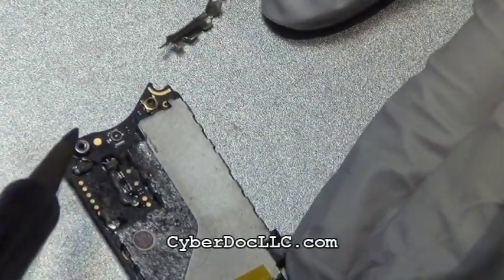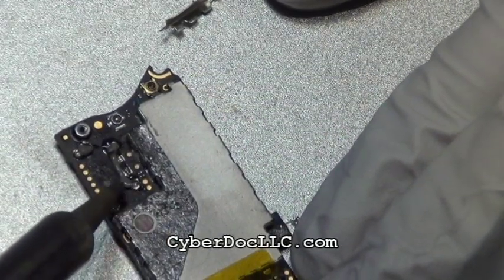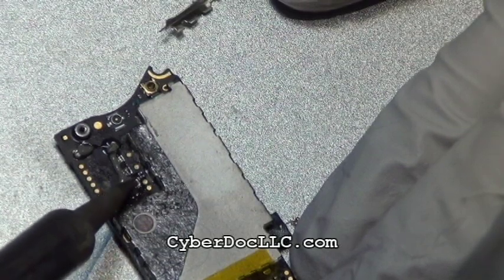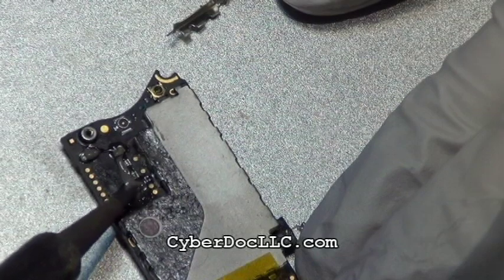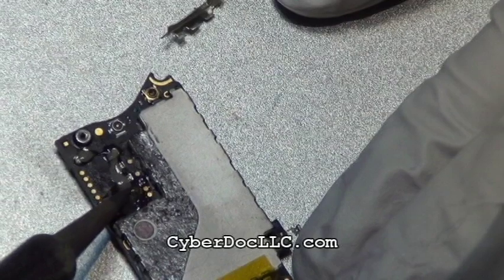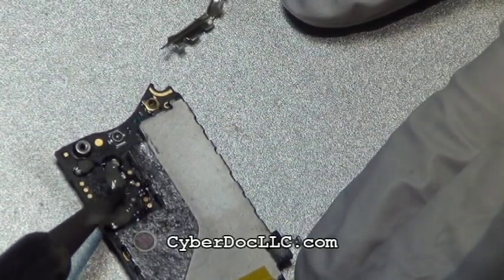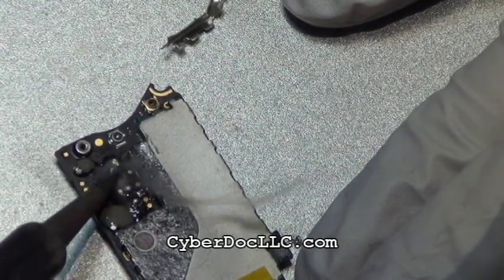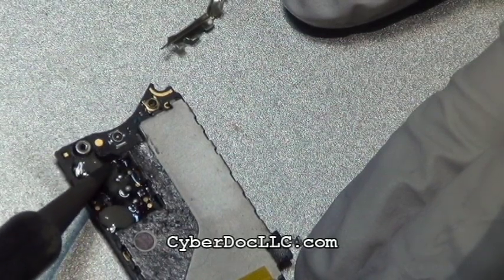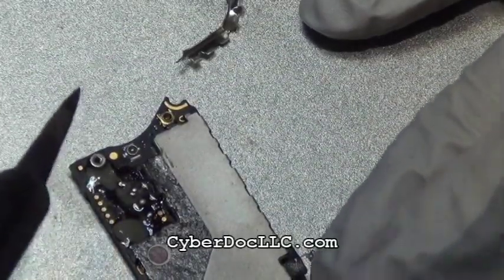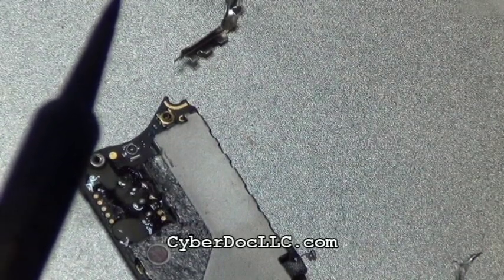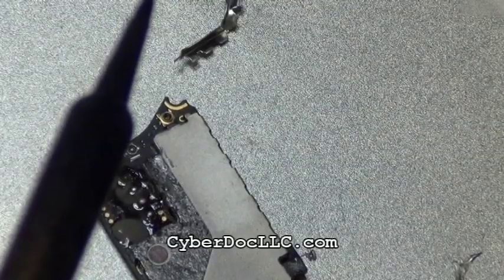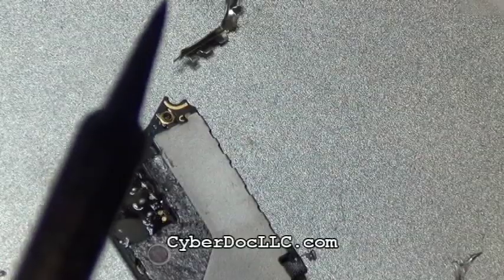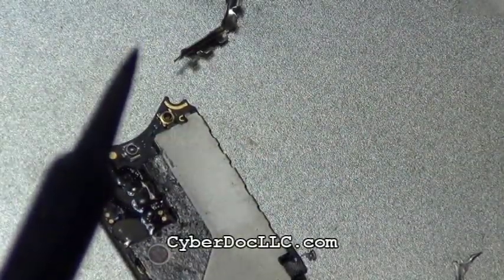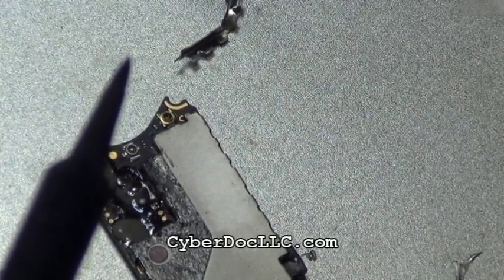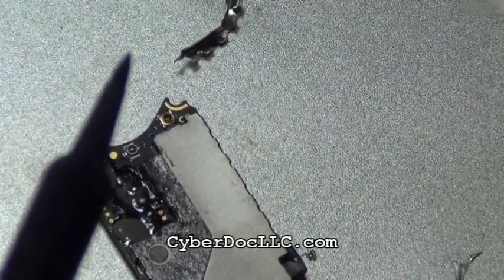So the idea is that you want to replace the existing lead-free solder that was already on the logic board, and mix it with the low melting temperature, also lead-free, solder paste. The reason is that I'm going to use the air bath method in this repair. If you keep the original solder, or use similar solder that melts at 230 degrees Celsius, it would make this repair very difficult, because you would have to use a much higher temperature, hot air or an infrared lamp, to heat out the original solder used by Apple. Instead of heating the logic board up to 300 degrees Celsius, which is very dangerous to the rest of the components and just too hot to work with, I'm going to use less heat to melt the solder.